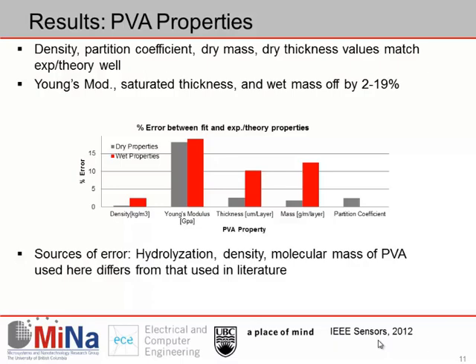And that's what this plot shows here, each of the properties of interest, and then the percent error associated with the fitting values as they compare to those which we expect. So in general, the partition coefficient, dry mass, and dry thickness values match experiment and theory very well. Well, the Young's modulus, saturated thickness, and wet mass are off by up to 2 to 19%. So right now, we believe that our main source of error has to do with the type of polyvinyl alcohol that we used, as we know that it was not the same as that which was used in the literature references. Specifically, its density, molecular mass, and degree of hydrolysis were different.